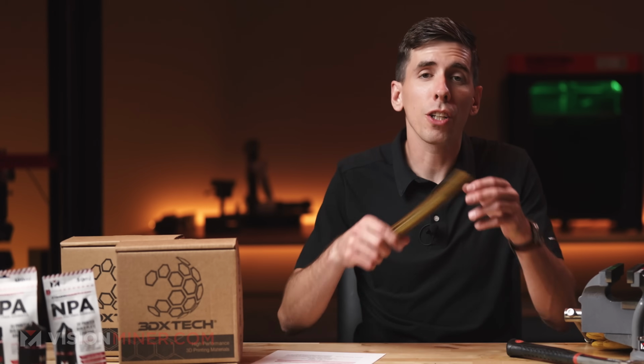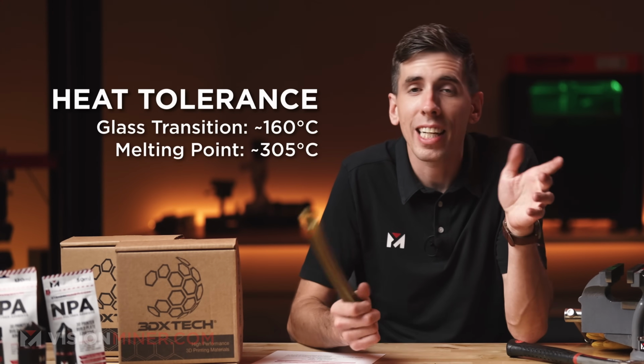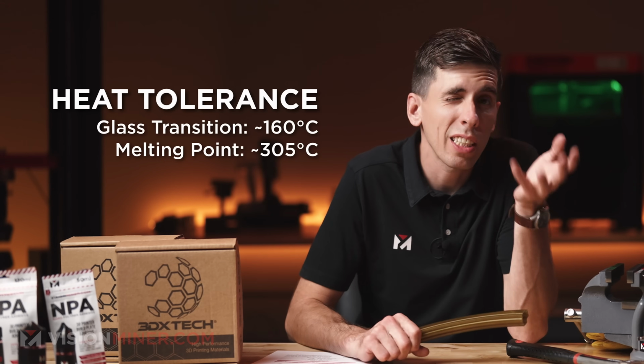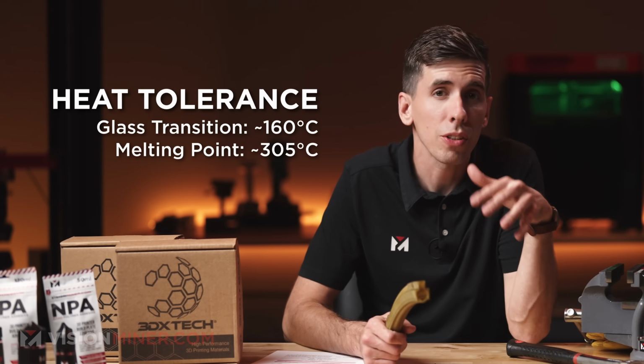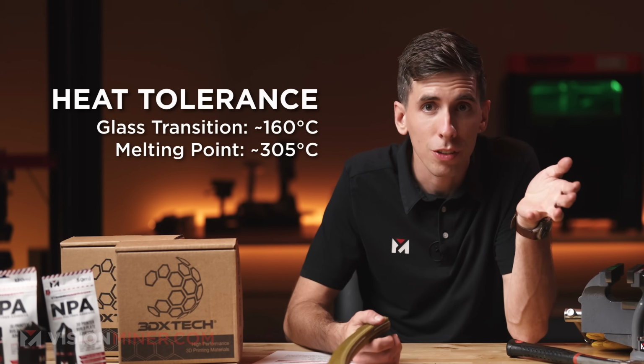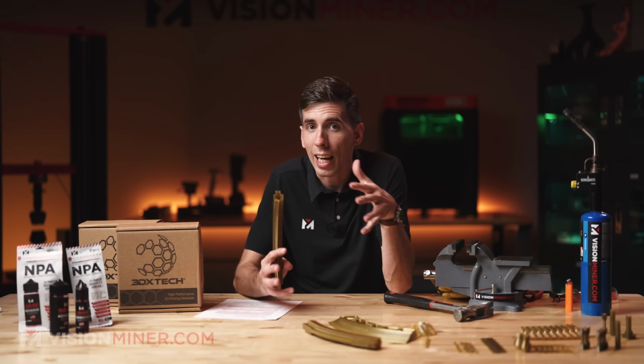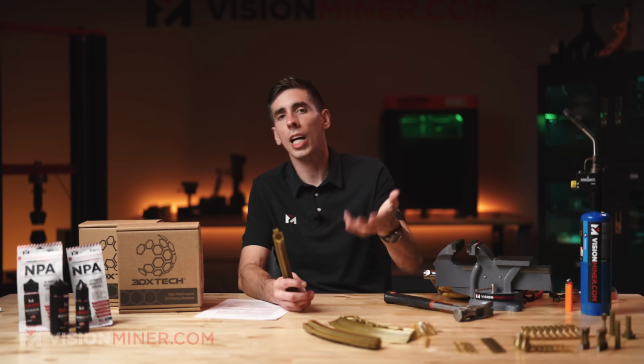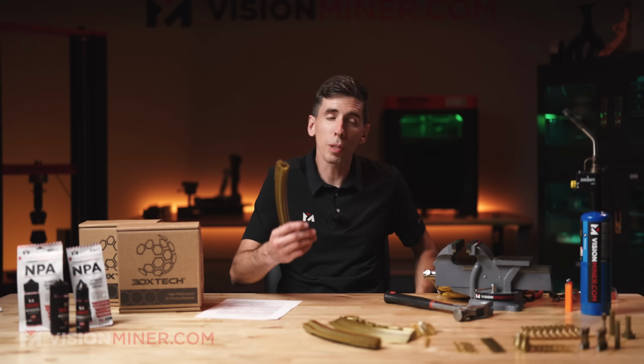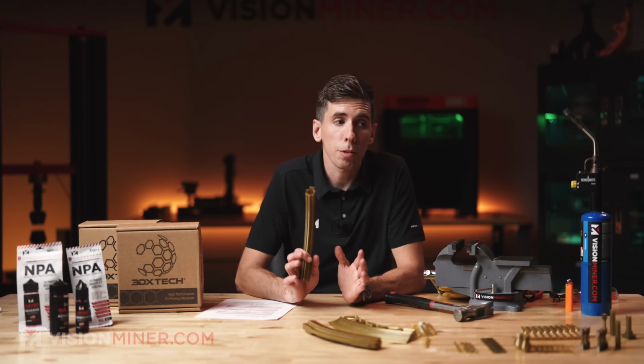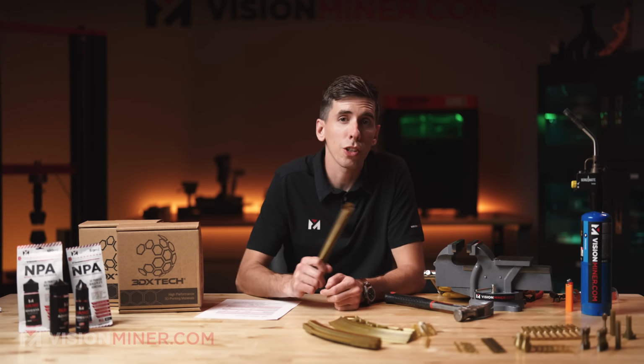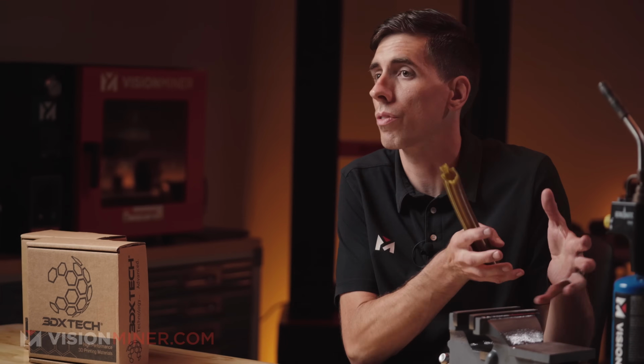As far as heat tolerance goes, PEKK-A has a glass transition temperature of about 160 Celsius, and it doesn't start melting at all until 305. So it can hold its shape in high heat environments where ABS or nylon or even polycarbonate would have pretty much already failed. So that's perfect for under the hood parts in automotive, high temp tooling, and anything that might sit near a heat source for long periods of time.